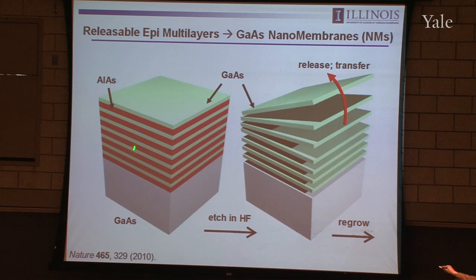And the nice thing about this kind of multi-layer stack is that if you etch down through the thin films that you're growing to expose the sidewalls, and you immerse this in a particular type of etchant, in this case hydrofluoric acid, it will etch away the aluminum arsenide selectively. That is, it etches this material a factor of 1,000,000 times faster than this material. And so after you grow that multi-layer stack, you etch down, you dip it in HF, and what you do is you release from the surface of the growth wafer multi-layer stacks of ultra-thin sheets of gallium arsenide.